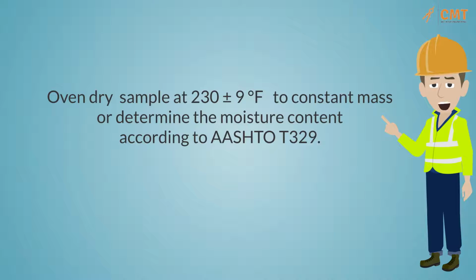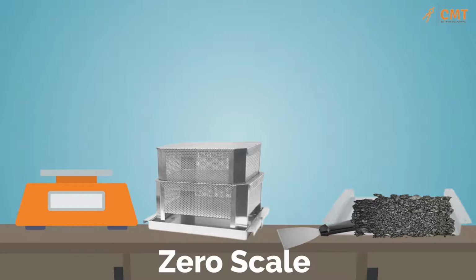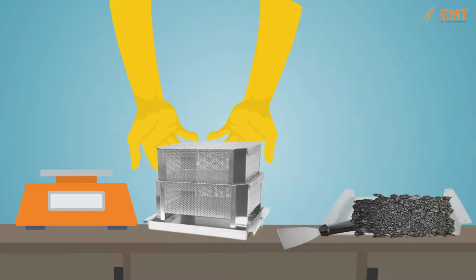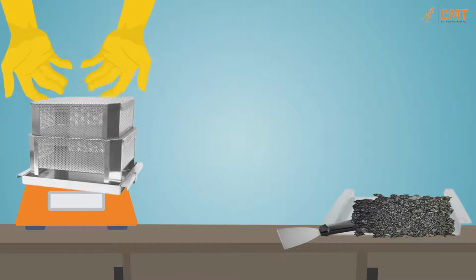Keep in mind that if the sample is not warm enough to separate, warm the sample at 230 degrees plus or minus 9 degrees Fahrenheit until it is workable. Do not heat the sample for an extended period of time. Once you have your sample, you need to zero out an external scale and place the basket assembly on the scale platform. You will record the mass of the empty basket assembly, then remove it from the scale.